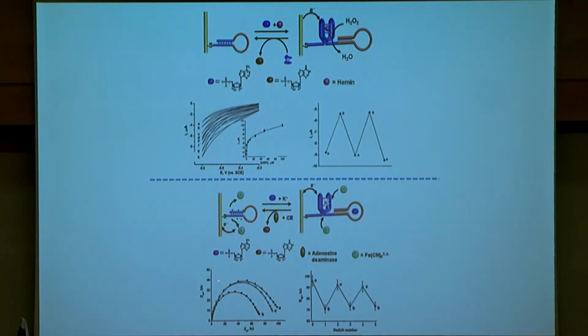amperometric responses of the electrode, but in reality, you can do it also by impedance spectroscopy, whereby you examine the interfacial electron transfer properties upon transforming the electrodes from the hairpin structure to the G quadruplex. For example, using ferrocyanide as redox reagent, the Faradaic impedance spectrum is strongly dependent on the structure of this nucleic acid functional electrode. In the presence of the slightly positively charged potassium ion stabilized G quadruplex, the electron transfer resistance is substantially lower, and we can sense the event by probing the impedance spectrum of the system.